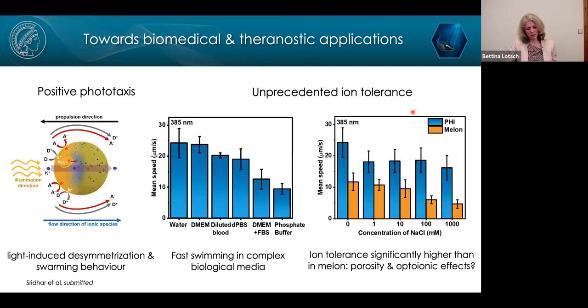And so I'm basically at the end now. What we've done lately, to be very brief, is look at different features in the system. For example, a quite surprising fact is that these micro swimmers are extremely ion tolerant. Normally you would observe that colloids cannot swim in high salinity environments, in high ionic strength environments, even ionic strengths that are just a few millimoles.